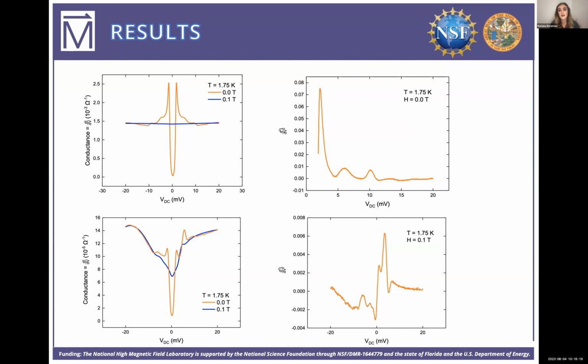On the right, I have a second harmonic measurement of this. This is kind of a derivative of the first, but we actually take this measurement straight from the sample by using a lock-in technique. And so these humps are related to the electron-electron correlations in the superconductor. Once we knew that these were high quality and we had a good process, I was able to start following the same procedures with samarium hexaboride, which is the material we know less about.